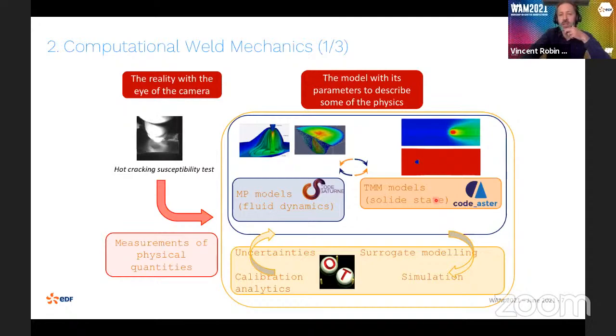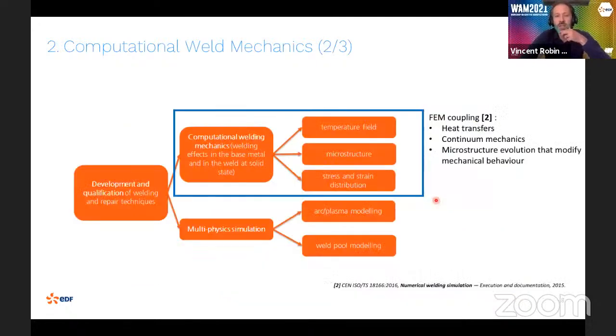So if we zoom in on this activity, which concerns computational welding mechanics, we deal with the welding effects in the base metal and in the weld at solid state. And we can address some issues related to temperature cycle through the component, to microstructure, and also to the evolution of stress and strain distribution. The approach is mainly based on finite element coupling of heat transfer, continuum mechanics, and also microstructural evolution that modifies mechanical behavior. And most of the approaches we develop, because they can be used for engineering purposes, are consistent with some standards related to numerical welding simulation.